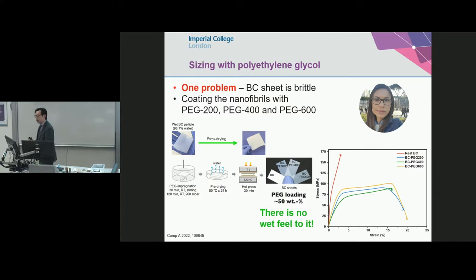One problem is that this thing is rather brittle, so it doesn't actually work as well. So Natalia came to the group a couple of years back and decided that, you know what, I'm going to take this pellicle, I am going to swap out the water with a high boiling point molecule, polyethylene glycol. So these are polyethylene glycol of 200 molecular weight, 400 or 600 molecular weight. So essentially, you soak them in polyethylene glycol, you dry off the water, the polyethylene glycol stays behind, infiltrates it, you squeeze the excess out, and you get, again, a similar structure. And now, in this case, instead of dried air, you actually have 50% polyethylene glycol in the system. And we actually see the whole thing becomes more ductile there.